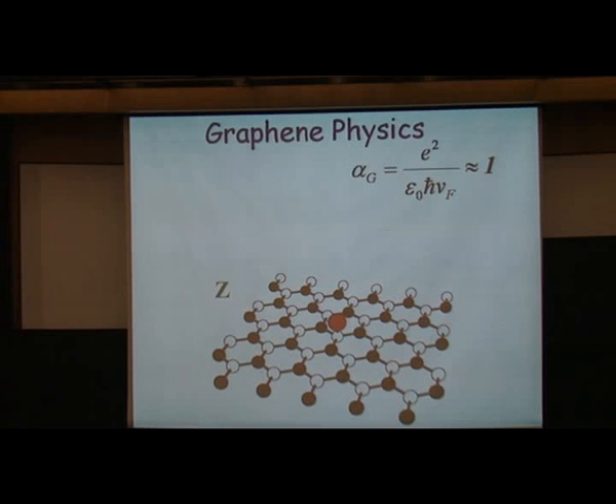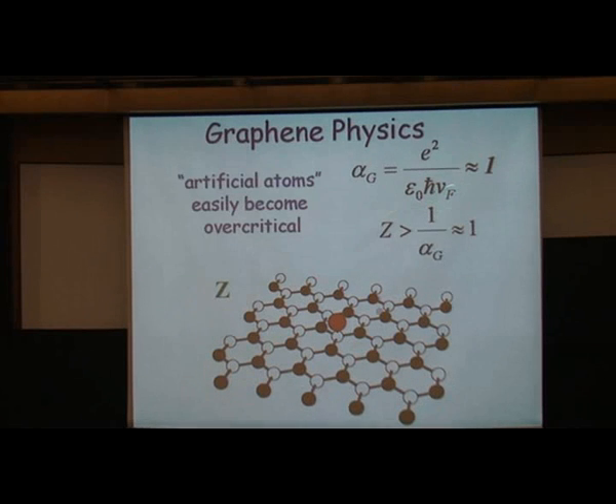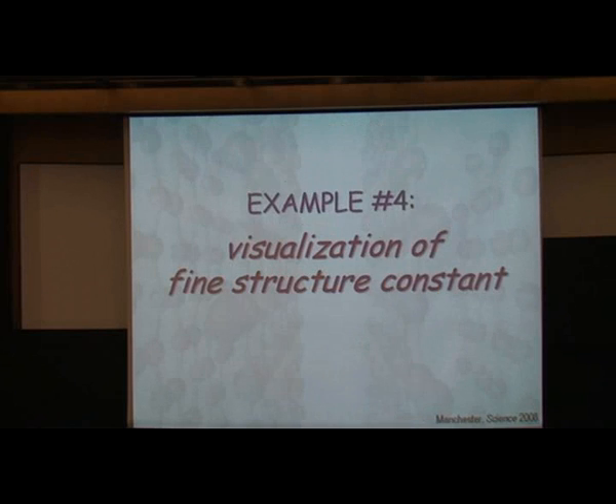Where graphene comes from, in graphene the coupling is described by the same constant, but instead of the speed of light you get an interaction velocity 300 times less than the speed of light, and all charged impurities in graphene become overcritical. It means that you can get all different sorts of phenomena related to screening and so on, and you can mimic this phenomenon, which is known for 60 years, of the fall on the center, but has never been observed. My next example is about,